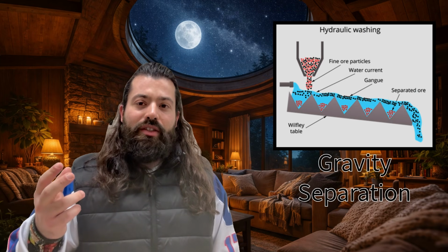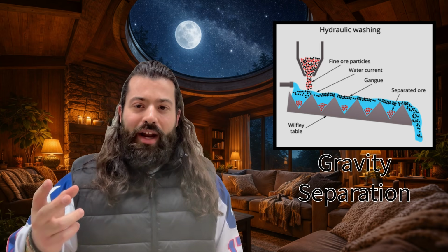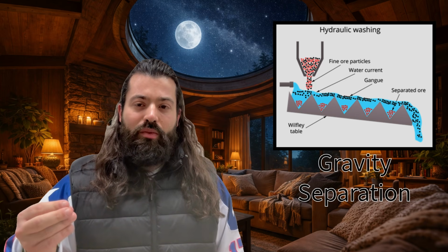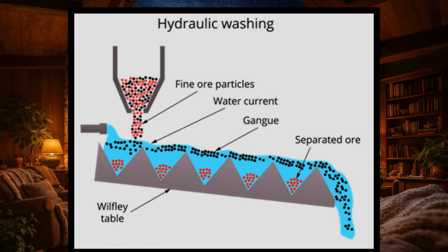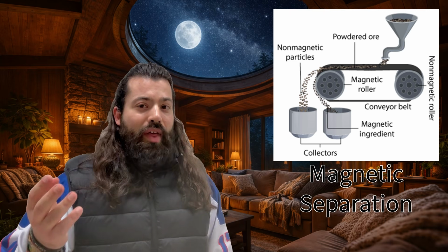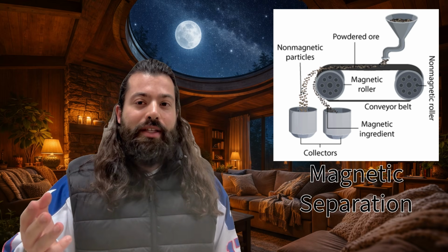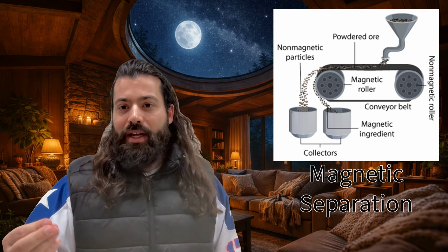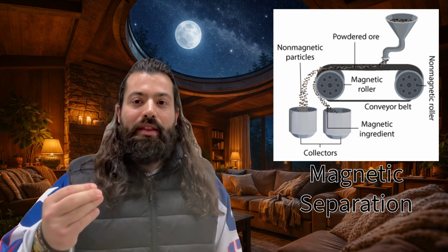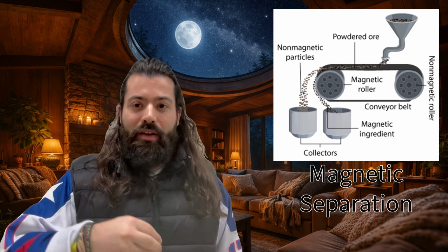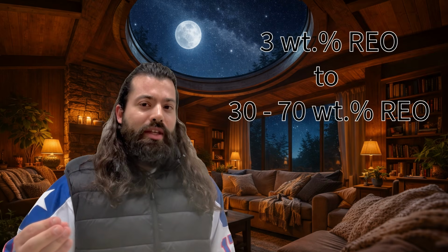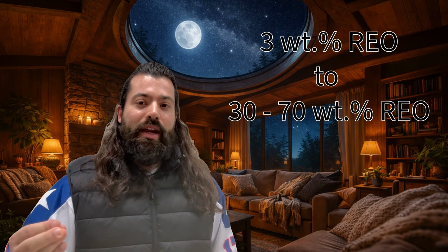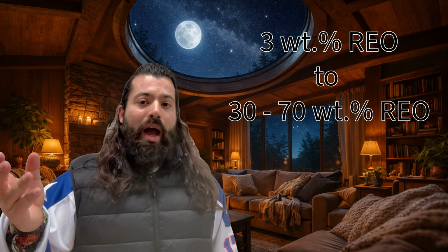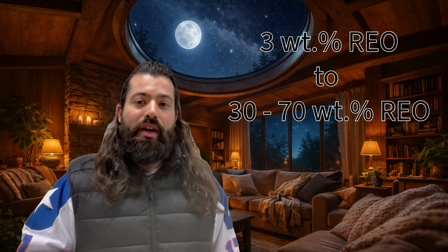Another technique is called gravity separation. The crushed material is introduced in a medium which is either water or air. Under the force of gravity, heavier particles settle at the bottom, while lighter particles are carried away. The third technique is called magnetic separation, and in this technique we just use a magnet in order to separate the non-magnetic material from the magnetic material. Using these techniques, we can upgrade our concentration from 3% to up to 30 to 70% of rare earth oxide.